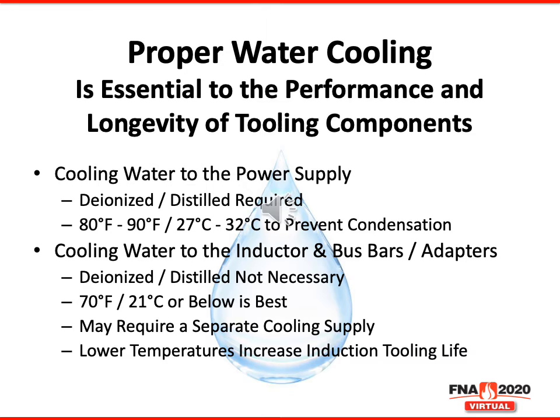For cooling the inductor coil, bus bars, and adapters, deionized or distilled water is not necessary. Cooling water for these induction tooling components is best kept below 70 degrees Fahrenheit. This may require a separate cooling supply. Through laboratory experimentation and real-world production trials, we have proven that lower cooling water temperatures can drastically increase the life of these components, especially in high volume, high power, short cycle applications.